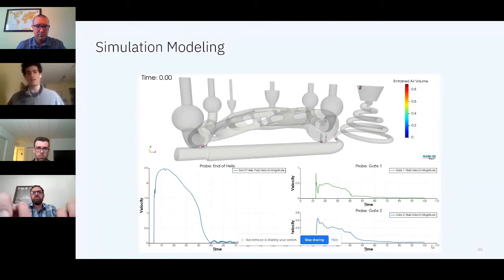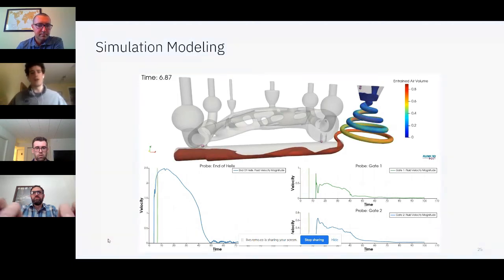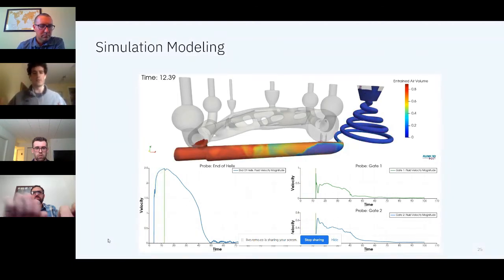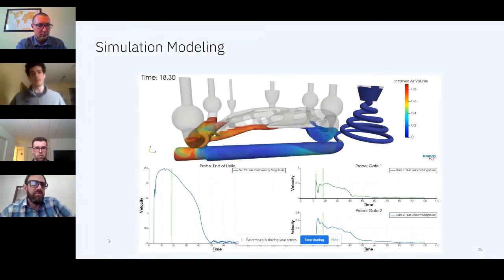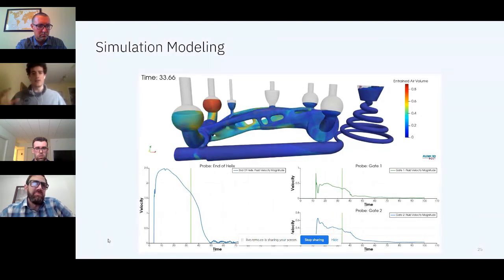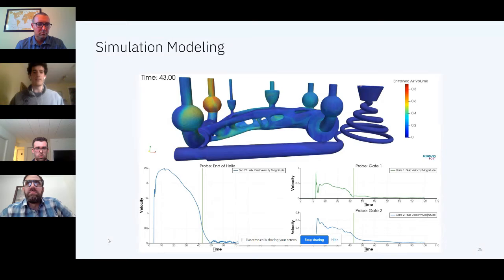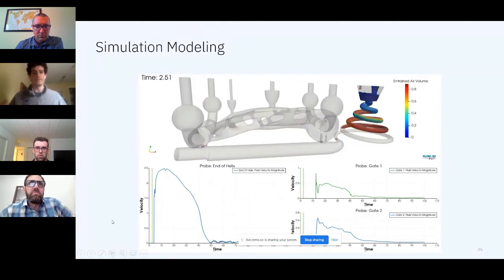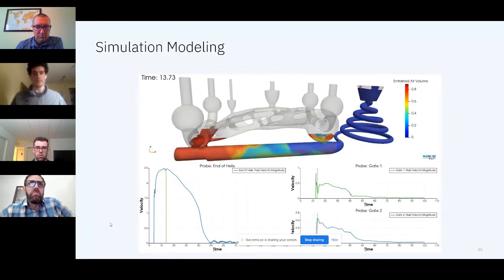And so here, if you play the video. So here is just the final model we had of filling with Flow 3D, where you see we have very slow filling, so we don't get splashing occurring during filling. And this is due to the conical helix sprue slowing down that melt, and also the long runner taking a while to fill up so we don't get turbulent filling, which will reduce our defects in this casting, which is especially important for the topology optimized casting where we don't have that high a margin for error with these small surfaces. So next slide, please.